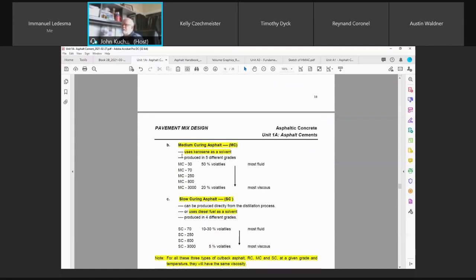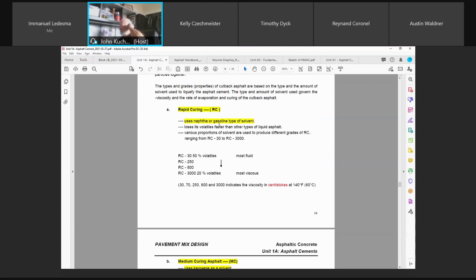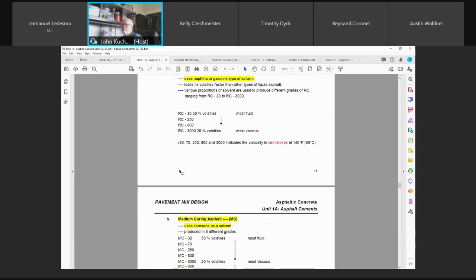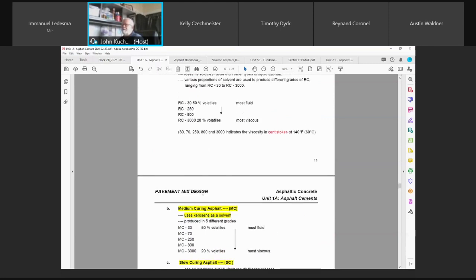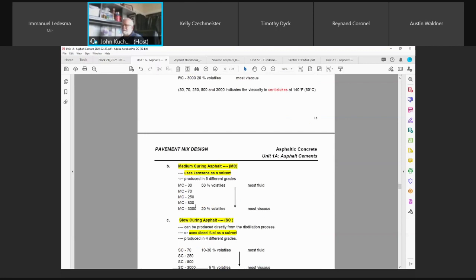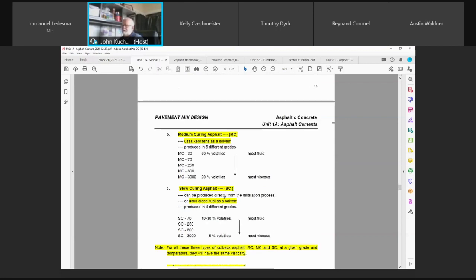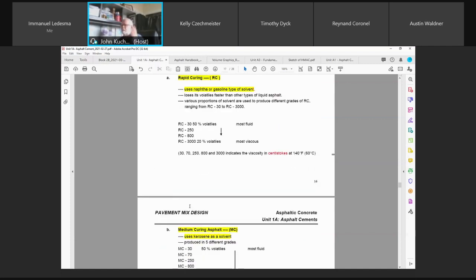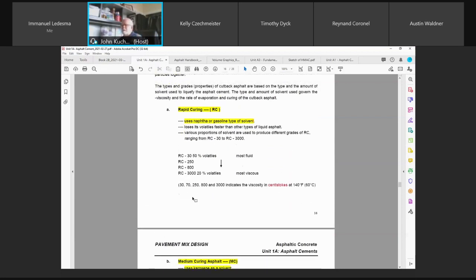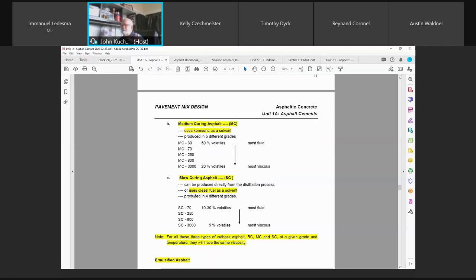Medium curing, now we use kerosene. So these are highlighted because these are important. Which solvent do you use to produce RC? Which one do you use to produce MC? Which one do you use for slow cure, SC, okay? So naphtha or gasoline, kerosene, and diesel. You can actually make an SC directly from the distillation process, but also just take the asphalt cements and cut it with diesel fuel and you'll make a slow cure. And these you'll see many times are being used for prime coats, tack coats. Place it on your granular base, or your asphalt pavement, adhere to it. Okay, so those are the three cutbacks: rapid cure, medium cure, slow cure, and we're using solvents.